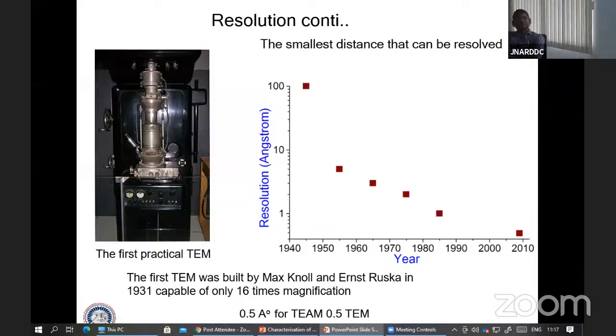The first transmission electron microscope was built by Max Knoll and Ernst Ruska in 1931. At that time it was only capable of about 16 times magnification. Around the 1940s, the best resolution we could get was around 100 angstroms, that means 10 nanometers, by TEM. But by 2010, it was around 0.5 angstroms for the transmission electron microscope.